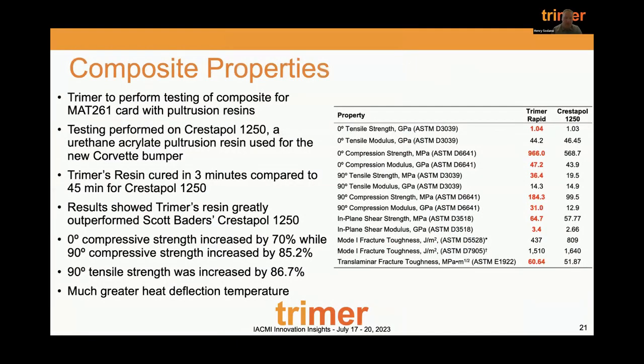And then the right image and the static images on the back, that's showing that even in one of the fissures, this is still an insulating material. So if we did have a fire, we shouldn't have a discharge event. Composite properties, I won't really talk too much about. You can look at those, but this is being compared to a Crestapol pultrusion resin system that's used on the current Corvette.